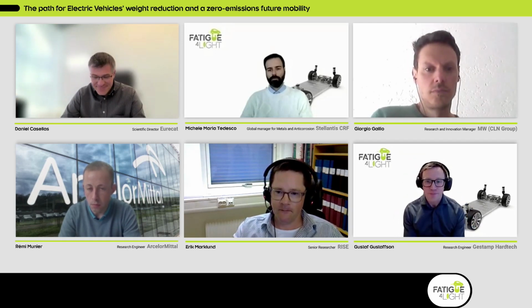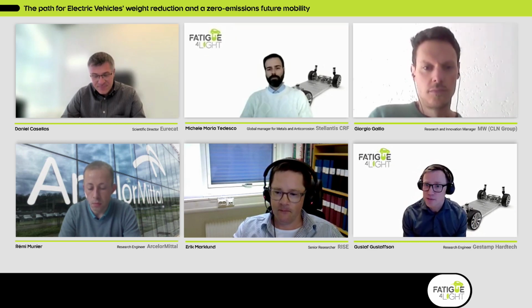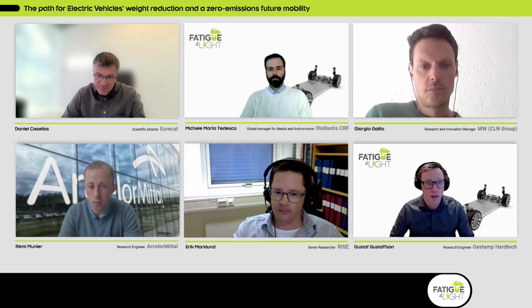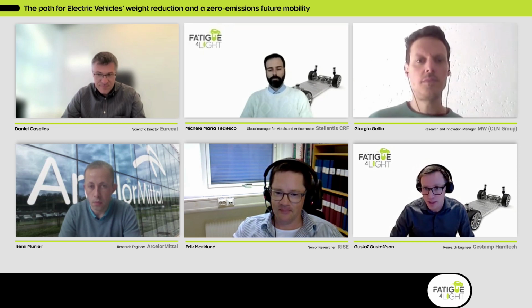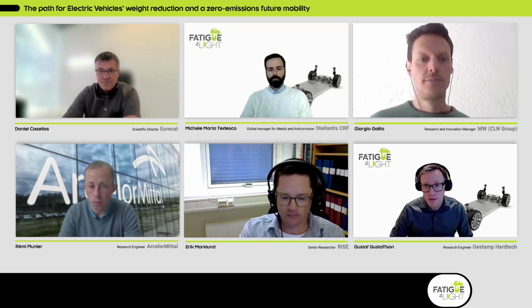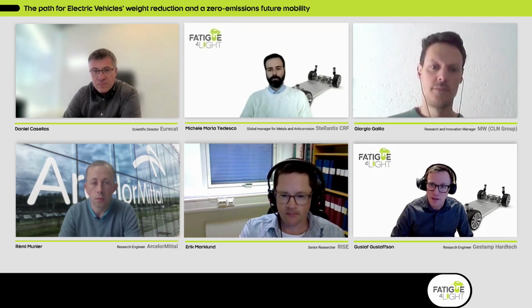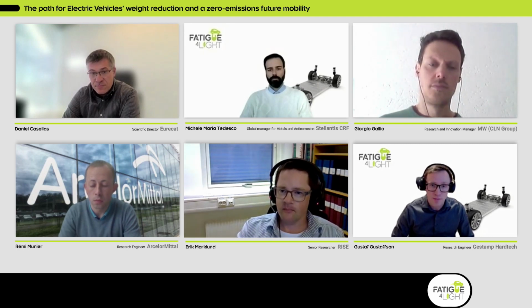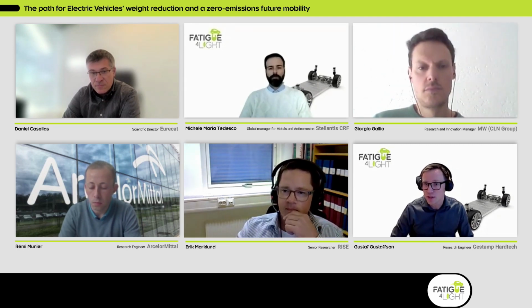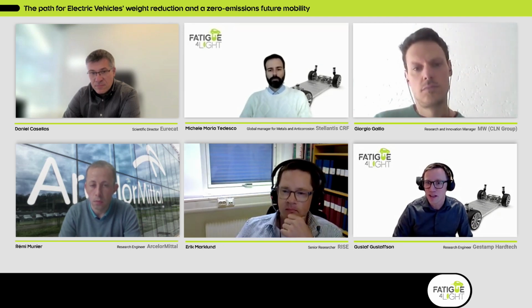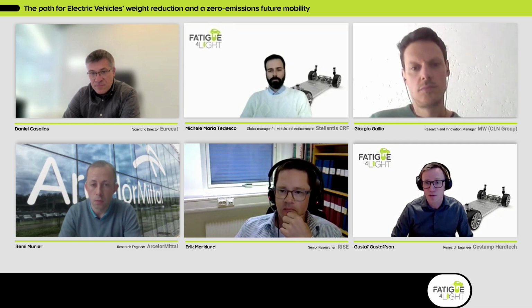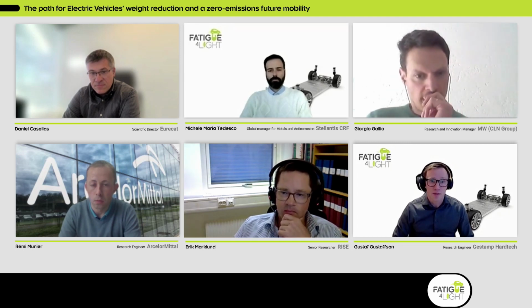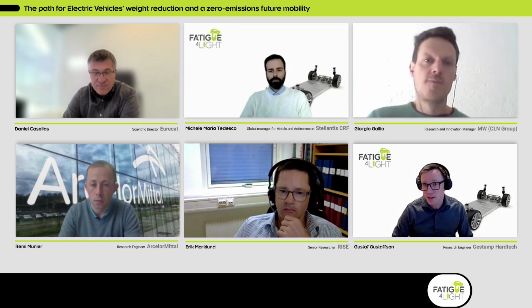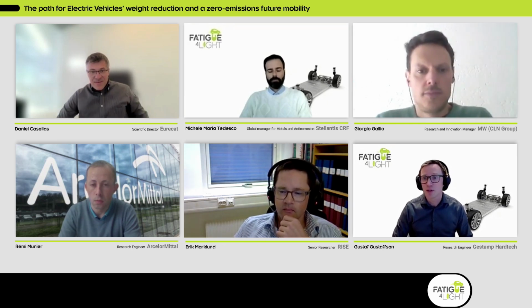I understand your question. As we saw this morning, Henrik from Scania was talking on this topic a little bit. If we have good conditions in the steel with good surface quality, then we have this relation between high strength and fatigue strength. So comparing a high strength steel with a yield limit of about 1000 with a cold forming steel with a yield limit of about 500, we see the potential of using this kind of material. This means that we can decrease the thickness and decrease the weight if we have this working properly.